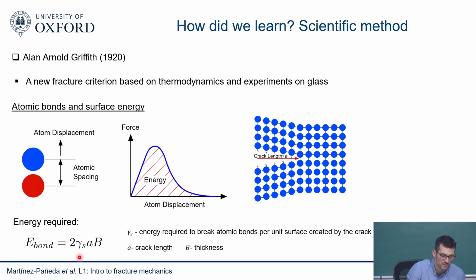That is 2 times gamma s, where gamma s is the energy required to break atomic bonds per unit surface created by the crack. Then you have a crack length a, and then you have a thickness, of course, because we should think in 3D. This 2D picture that we're seeing has a thickness of b, so that is the area. So you're breaking a lot of atoms. The energy that you need to create a surface is gamma s. Because we have two surfaces it's 2, and because we have a crack of length a and a plane of thickness b, we multiply by ab. That's the idea. So that is consistent with thermodynamics.